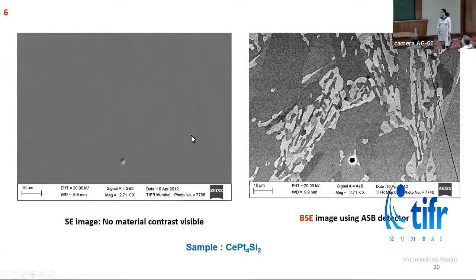I mentioned Z contrast imaging using SEM. So this is such a sample of cerium platinum 4 silicon. Here, by looking at the topography of the sample, we feel that the sample is homogeneous. But when we image the same sample using an ASB detector, that is an angle selective backscatter detector, we see a very colorful sample. It means the sample is not homogeneous. Here, the bright regions are made up of elements which are high Z or high atomic number, and the gray regions are made up of elements which have low atomic numbers. This can be confirmed by doing a point mode EDS analysis on the sample.